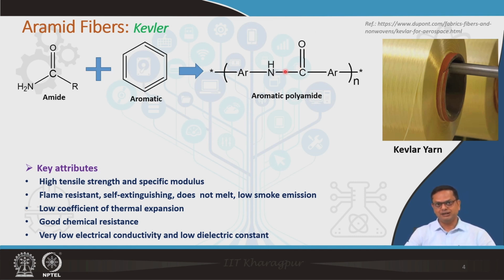You can see that has been done here. CONH is residing between two aromatic rings, but there are multiple combinations by which you can have amide and aromatic groups attached. For example, you can have a couple of amide groups together and then one aromatic, or two aromatics together and then one amide group. There could be multiple variations by which you can attach amide and aromatic groups, and we do not call all of them Kevlar or aramid fiber. By the way, Kevlar is the commercial name. There are other commercial names as well, like Technora, but basically it is an aramid structure.